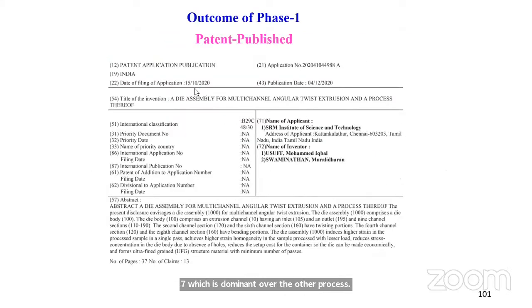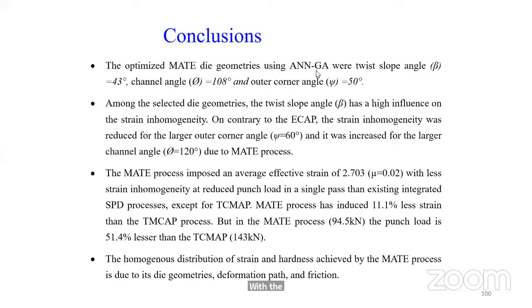So the conclusion is the optimized MATE die geometries using ANN-GA, where slope angle beta is 43, channel angle 108 and corner angle 50. Among the selected die geometries, beta has a high influence on strain homogeneity, and contrary to ECAP, the strain inhomogeneity was reduced for an outer corner angle of 60 degrees and it was increased for the larger angle of 120 degrees due to the MATE process.